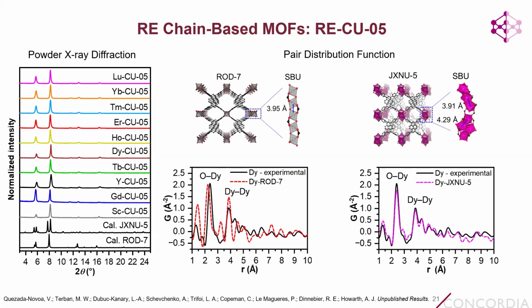And so from that high-res powder X-ray diffraction data, we still were not able to do a proper Rietveld refinement due to the severe lack of Bragg reflections in this powder pattern. Victor was able to do a Pawley refinement where he found that the unit cell parameters for Cu-05 did match pretty well with those of JXNU5. But of course, just a Pawley refinement still doesn't really tell us that much about the overall structure.